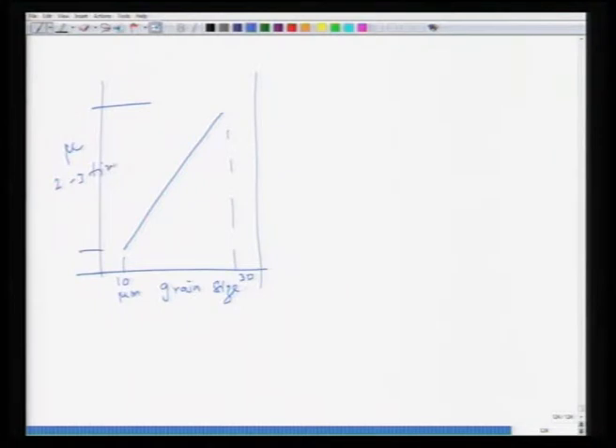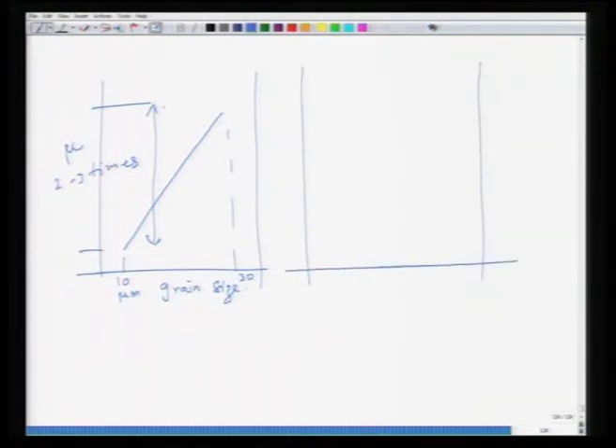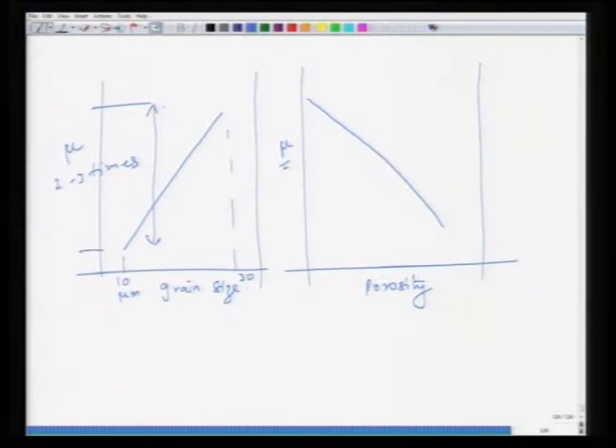For example, in a model system the variation of μ as a function of grain size shows that it increases as you increase the grain size from about 10 microns to 30 microns, and this increase in permeability can be 2 to 3 times. Porosity also has a dominant effect — it tends to reduce the permeability of ferrite materials. Both grain size and porosity are a function of the way the material is made, and this has a profound effect on the properties, especially the permeability of ceramics.